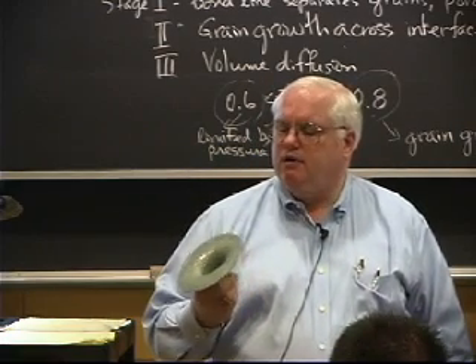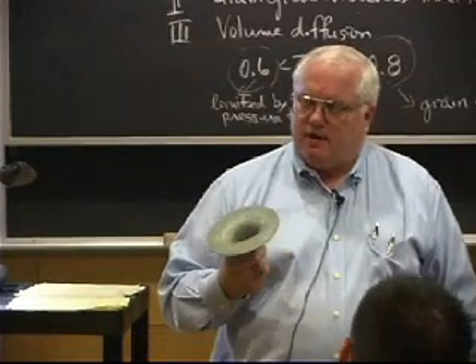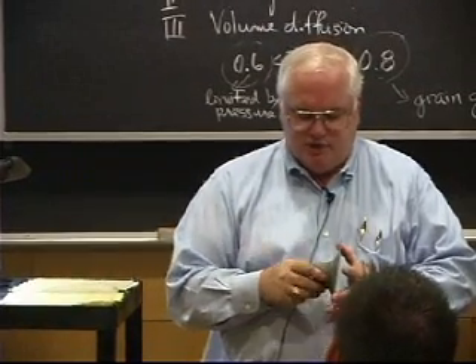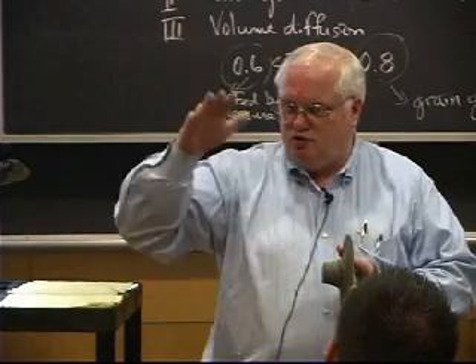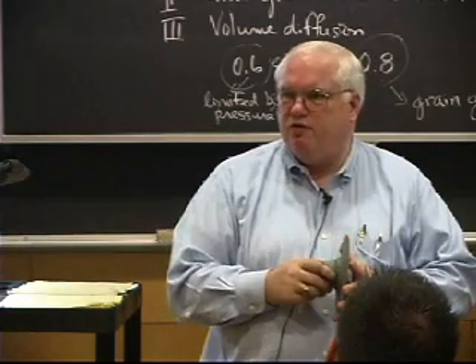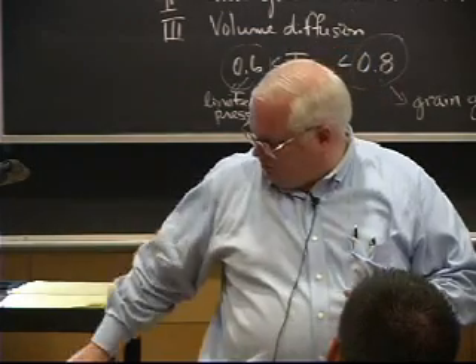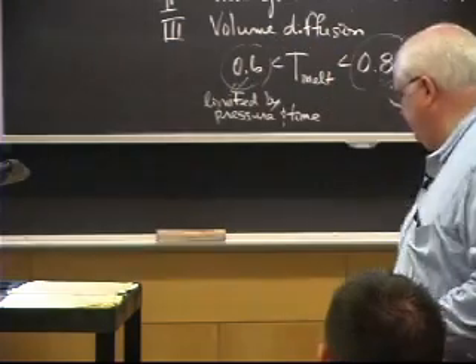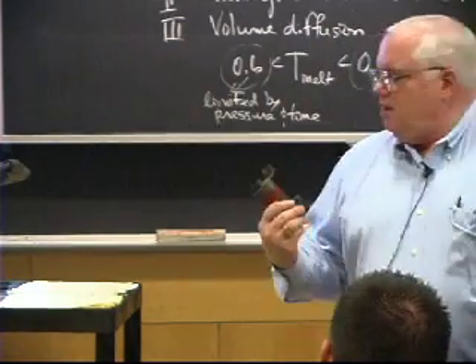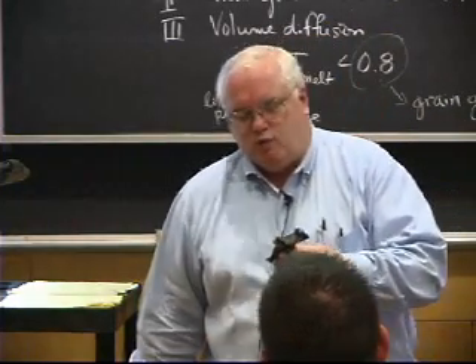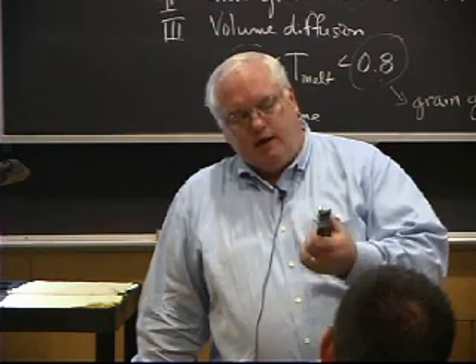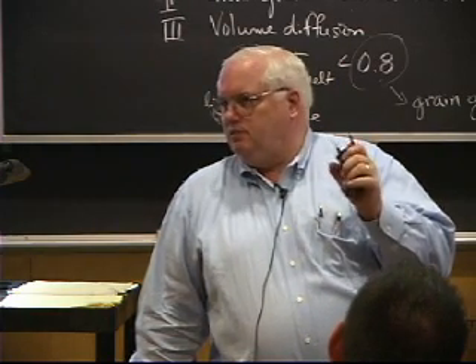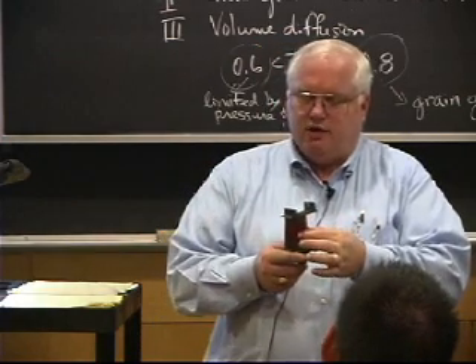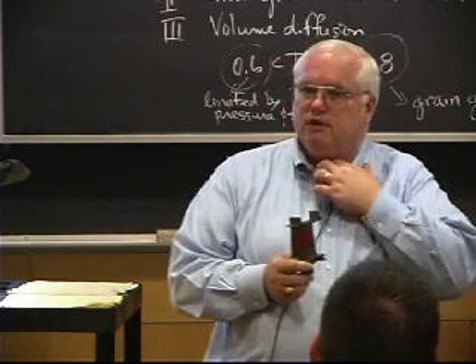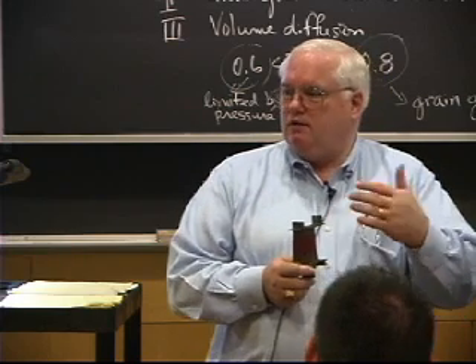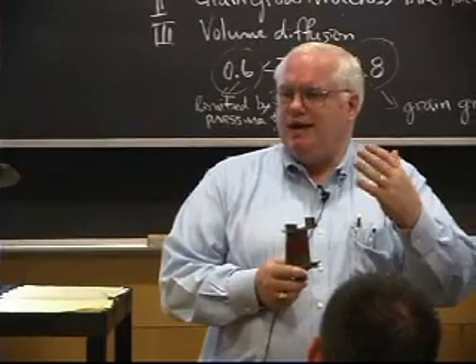Okay, so titanium will dissolve away its oxide, and so it forms nice, clean, contamination-free surfaces when you heat them up for diffusion bonding. And it has another property: you can cycle it through its crystal structure change, and you can get very, very fine grain size. And if you get very fine grain size, it turns out, remember this, well, I have a turbine blade here somewhere. Here's a turbine blade, or vane. When they first started making jet engines after World War II, they used just regular old cast stainless steel or whatever, with a bunch of grain boundaries, and they may only have been able to operate at 1,200 degrees Fahrenheit in the engine back then. And by 1970 they had crept up to around 1,800 degrees Fahrenheit.